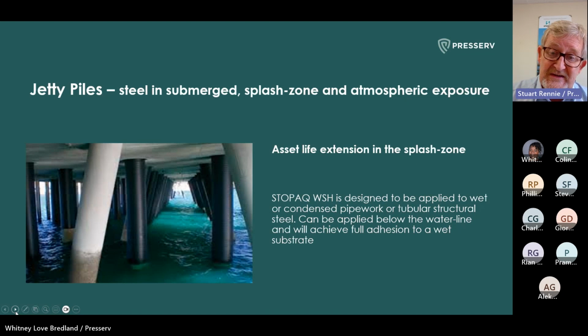Now, out of sight, out of mind, perhaps, but we have this product, we have this capability of arresting corrosion for 30 plus years, even longer, again, if it's applied by a qualified and certified applicator. Simple 3-coat system here with the WSH, the intermediate coat, then the outer wrap. And this will ensure full adhesion to the wet substrate below.